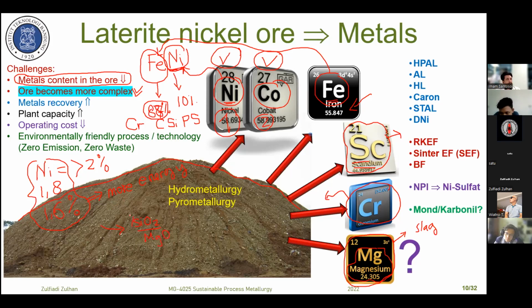Usually, the ratio of percent silica to percent magnesia in the ore should be around 1.8. Now this kind of ore is rare, difficult to find. The silica to magnesia ratio tends to increase. Now, in some locations, we have information that the silica to magnesia ratio is around 1.5 or around 2.5, or in some locations close to 4. It's very challenging for us to process. How to do it is a big question. Actually, not in the future, but right now.